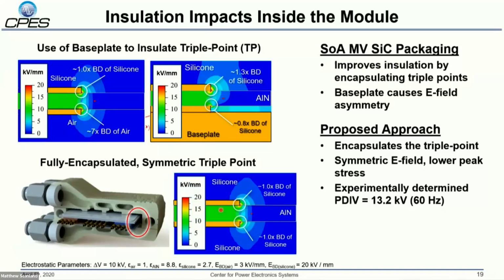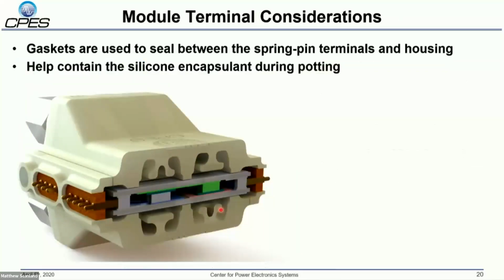So we remove that asymmetry and we maintain this nice symmetric electric field, which means both the top and the bottom side of the substrate have an electric field strength of about 1 times the breakdown strength of silicone. So we're able to eke out a little bit more electrical performance out of this than you might normally be able to do with a base plate. And this has been experimentally verified. I partial discharge tested these substrate samples at our lab in the basement of Whittemore and found that we were able to do about 13.2 kV PDIV at 60 hertz on these substrates. So sufficient for 10 kV operation.